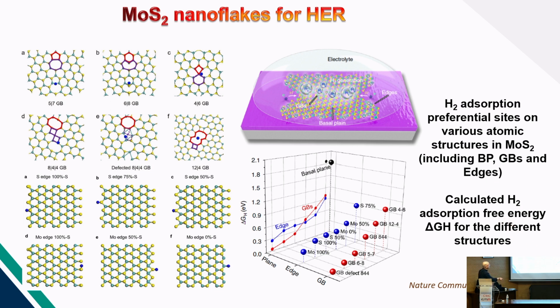You can calculate the hydrogen adsorption free energy, and then what you see is that the grain boundaries are working much better, or the energy in order to break the water molecule is much, much lower in the case of the grain boundaries, this case of grain boundary, than the basal plane, that, as you see, is really huge. You need a lot of energy. If you only work with molybdenum disulfide with a perfect basal plane, the 001, you need a lot of energy in comparison to this type, for example, of grain boundaries.